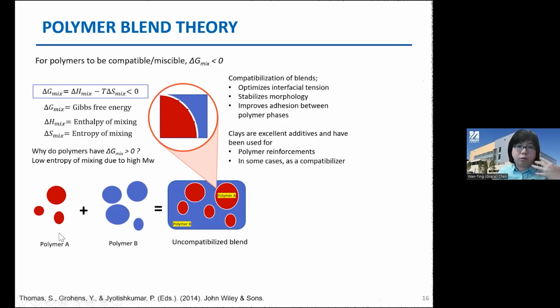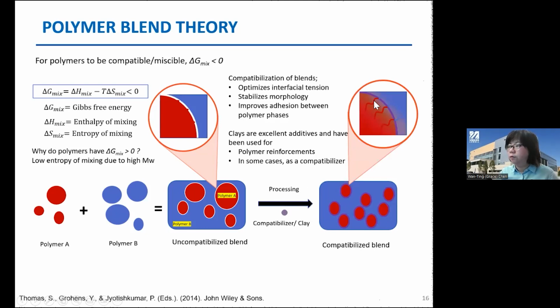And here we are just showing you the binary blends. In the project, we actually achieve ternary or quaternary, and so on and more. So we consider two types of compatibilizer here. One is the polybutadiene. It's also part of the polyolefin family, but it is a rubber. And we also adopt this clay and try to use the polymer processing to exfoliate it, making sure it can be well mixed in this polymer blend. So after that, hopefully we can improve that, and you can see that these two phases now are being mixed better compared to before. There will be a very distinguished boundary layer.